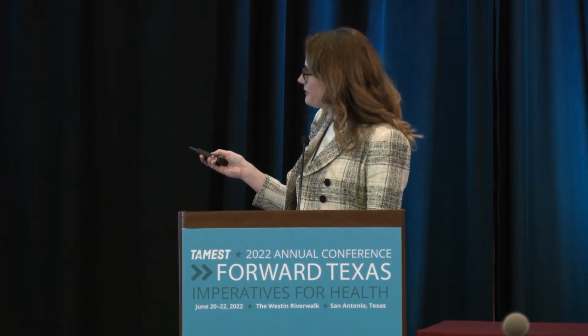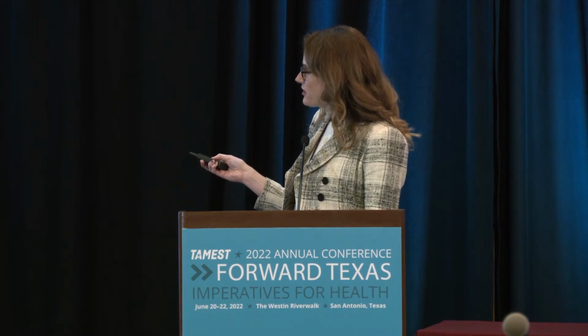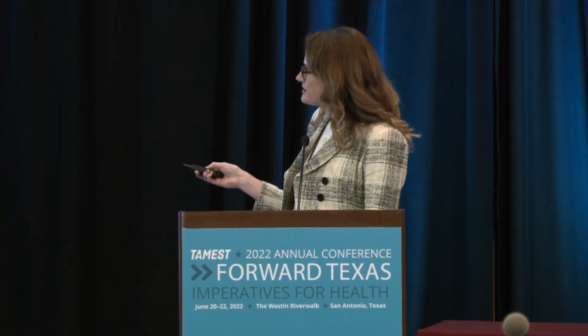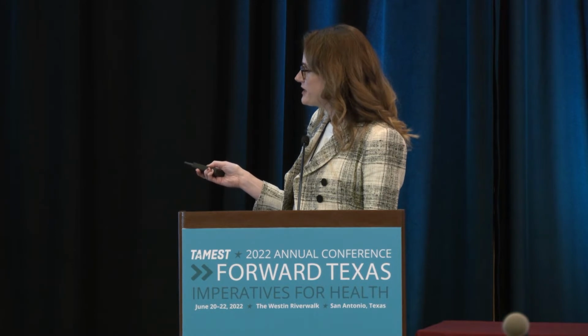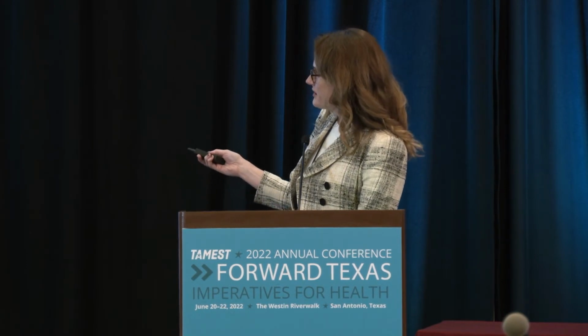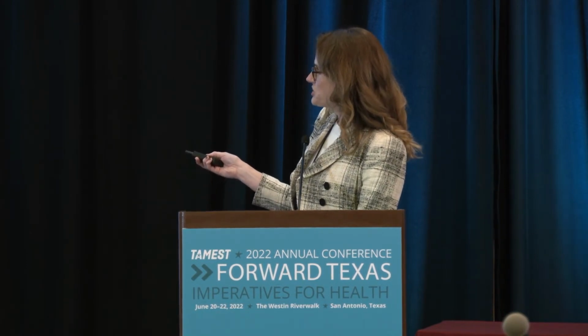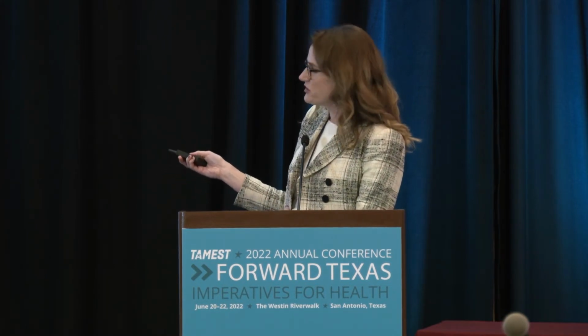So PTMA is this polymer here. It has an aliphatic backbone, which means it's a hydrocarbon, and then its pendant group is a TEMPO group that has a stable nitroxide radical. So we can synthesize this polymer in our lab any which way we like, and it's quite water stable, temperature stable, air stable, so it's really tolerant to a chemical engineer like me. And we can oxidize it and reduce it reversibly by exchanging an anion, any type of anion you like. Meanwhile, you're exchanging these electrons, which is how you store charge.